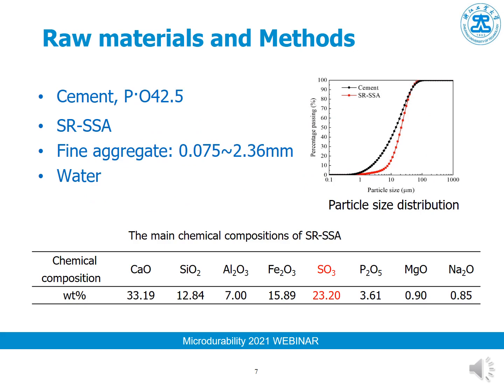The raw materials in this study included the cement, the sulfate-rich sewage sludge ash, fine aggregate, and the water. And from the table, we can see that the sulfate content in this ash is more than 23%. So there is a lot of sulfate in this kind of ash.